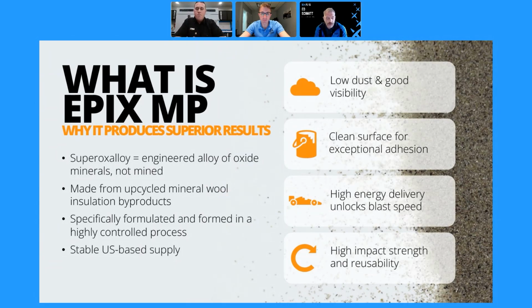So, we've got customer data that would say that you're correct, Moose. One customer on the industrial side that blasts tons and tons of material in weeks' time switched over from aluminum oxide. Now, this was in a much more coarse gradation of our material, but they switched over from aluminum oxide to the 10X product. After, I think, a few months, they came back and said that they had noticed their hose life went from 300 hours on the aluminum oxide to 600 hours with the 10X product.